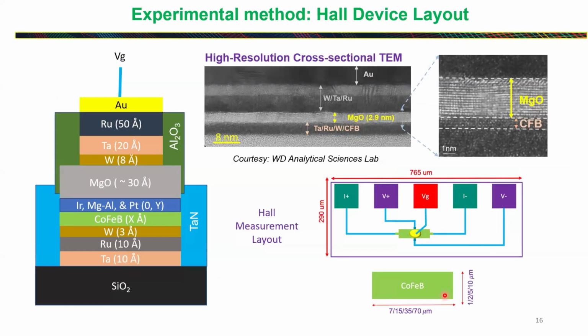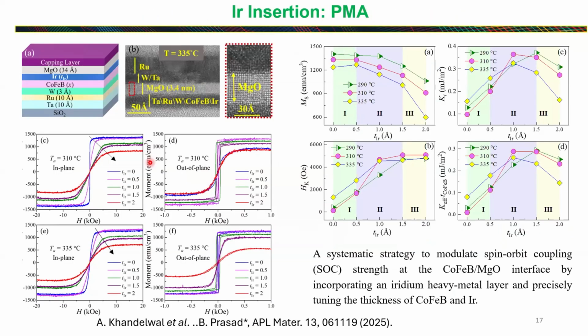So we introduce a thin layer of iridium. We have done many experiments: iridium, magnesium, aluminum, platinum. But today I'm showing only the iridium work. So we introduce a thin layer of iridium between the cobalt-iron-boron and MgO, and we make a Hall structure with that. And then we have done a post-deposition annealing experiment to check at what temperature you get the highest VCMA and PMA.